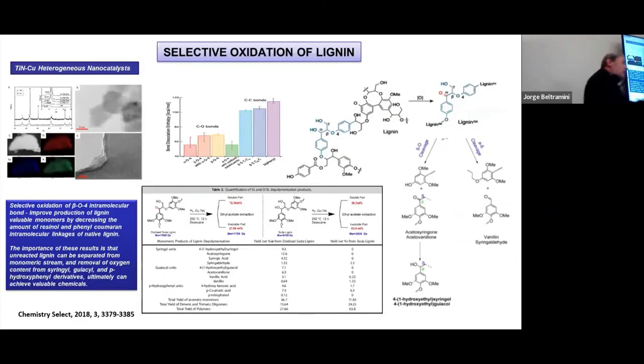And for the natural lignin, we study one particular bond, the beta-O4. The beta-O4 bond is one of the most important bonds in lignin, but it's one of the most difficult to break. If I break the beta-O4, I break practically the other structure of the lignin, so I get too many components. It's not useful. Through a study, what we came to the conclusion is the problem is with that bond dissociation enthalpy, okay? This is the original bond dissociation enthalpy of the beta-O4.